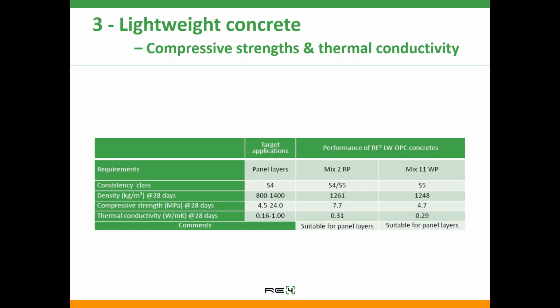In terms of compressive strengths obtained, the compressive strength with the rigid plastic was 7.7 megapascal at 28 days. There is a column saying the target application, its panel layers, and the compressive strength at 28 days can be anything between 4.5 and 24. So with the mix 11, the wood and plastics, the compressive strength is near the lower part of the range, achieving only 4.7. However, these are for thermally insulating concretes, and therefore what is important is the thermal conductivity of these concretes, which was measured and was found to be below 0.31 and 0.29, which are towards the lower part of the range that is normally required, which is 0.16 to 1.0.